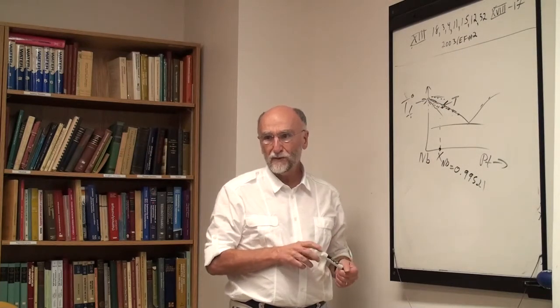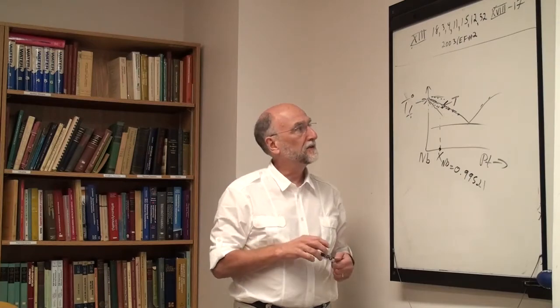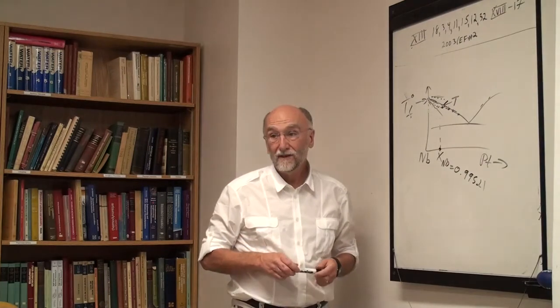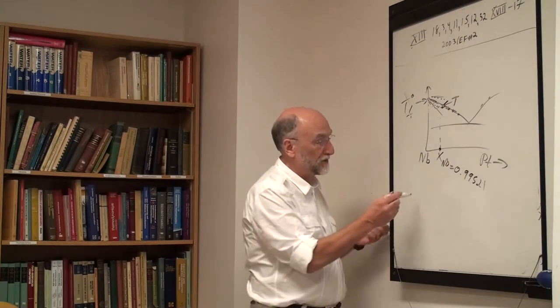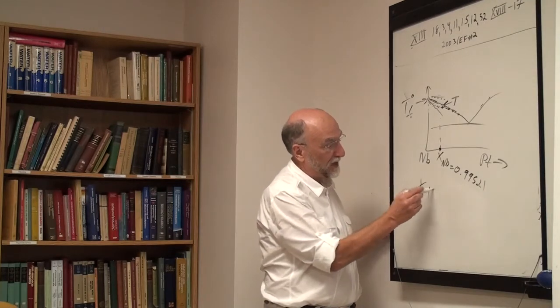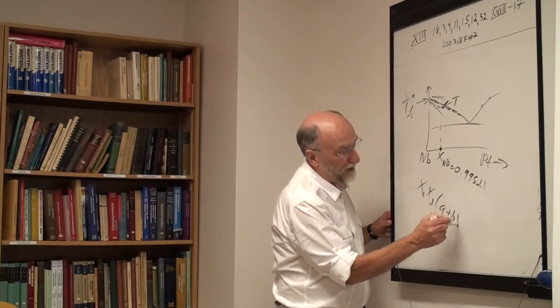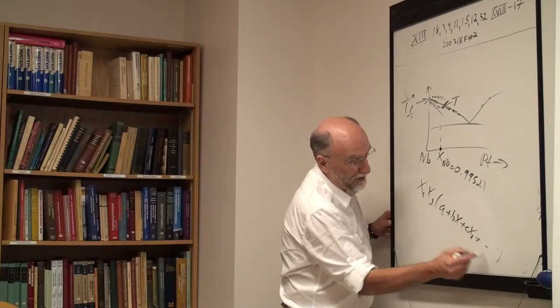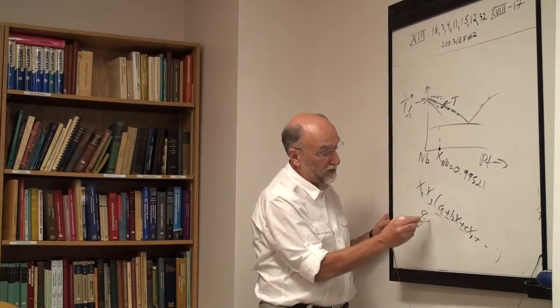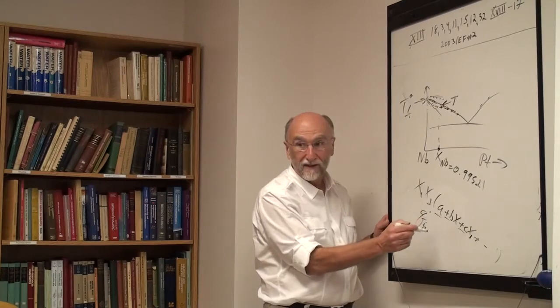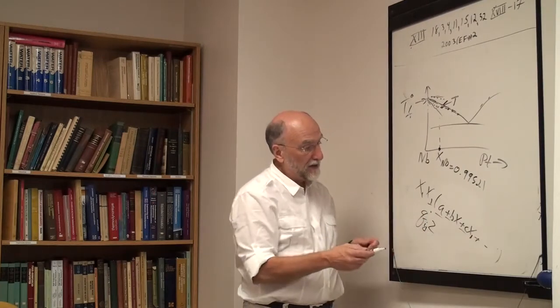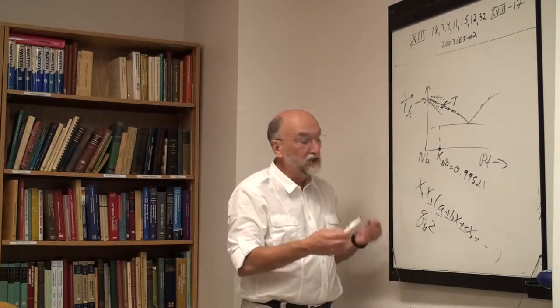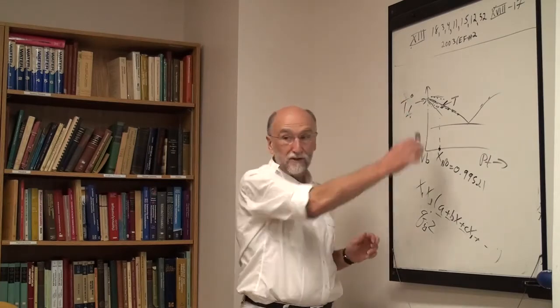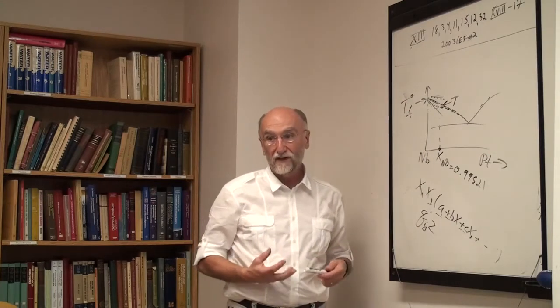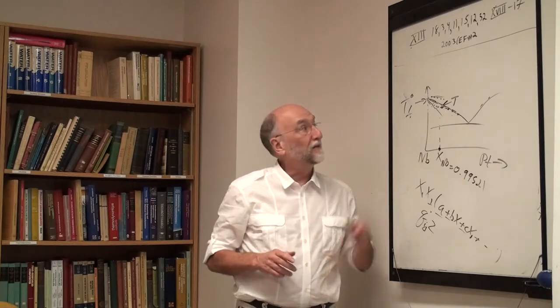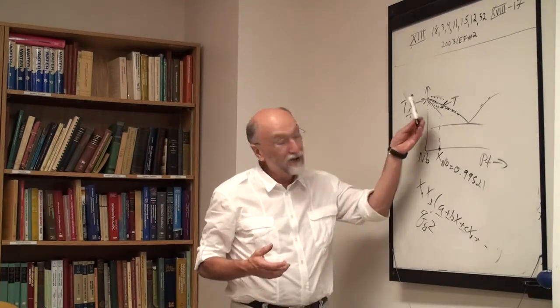The coordination number? Yes. No, that's nothing to do with it. But yeah, that will have no effect either. I'm talking about the expansion terms. You have x1, x2 times a plus bx plus cx squared plus d, these terms. What you call the q terms, the qij. Yeah, but none of these terms have any effect. No G-excess terms will have any effect on the limiting slope. It's only affected by the ideal term, and the heat of mixing, and the solid solubility.